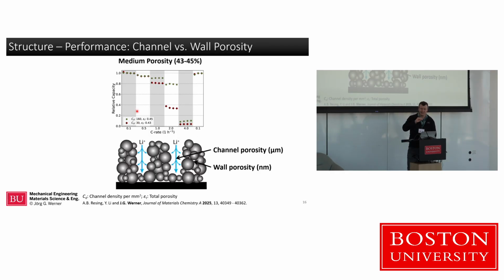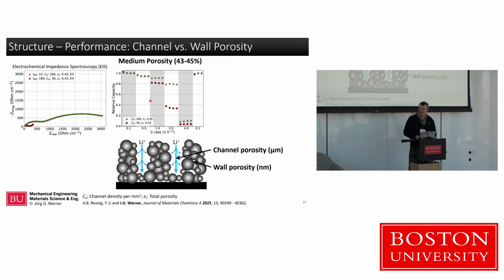Now, this is just really the blank capacity that we get out of these electrodes at different rates, and we usually do it 4 or 5 times per rate to make sure they're stable at that rate. Right? There's other measurements we do, like electrochemical impedance spectroscopy, which tells us a little bit about the resistance that our system has. And interestingly enough, when we do that, it's a very common analysis method in batteries and electrochemical systems. We find that the resistance of the one with very few channels, so more porosity in the wall, is much lower than the resistance of the one that has a lot of channels but has a very dense wall, which is the opposite of what you see in the cycling data. So the resistance measurement itself doesn't really tell us a lot. In fact, looking through all our data, this resistance measurement, which is an AC impedance measurement, seems to really just probe that local environment around the particles. It doesn't probe the electrode level over tens and hundreds of microns, which is really the relevant length scale that we care about to a big part when we charge full batteries.